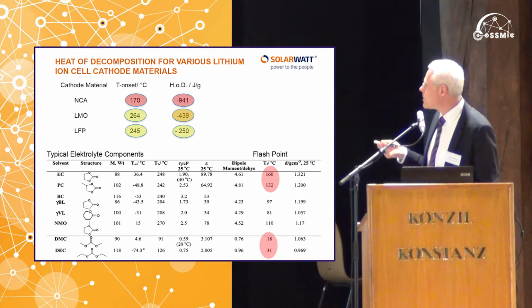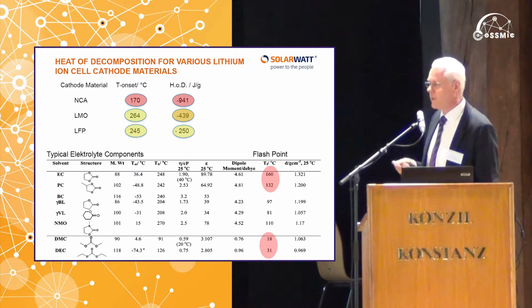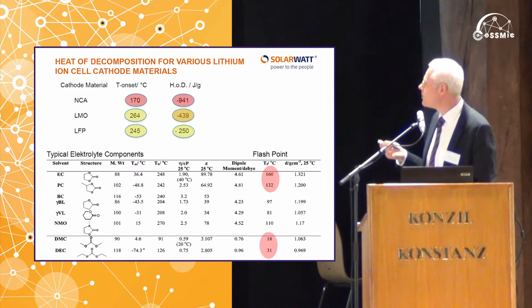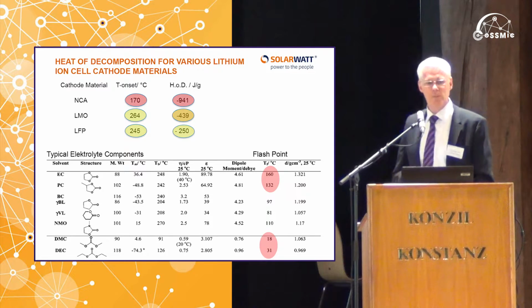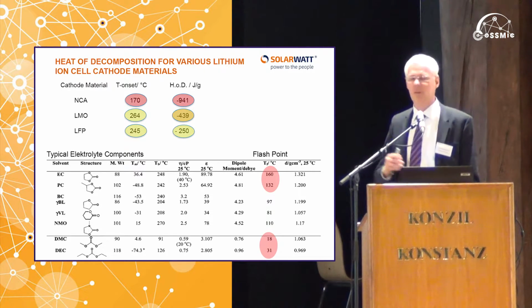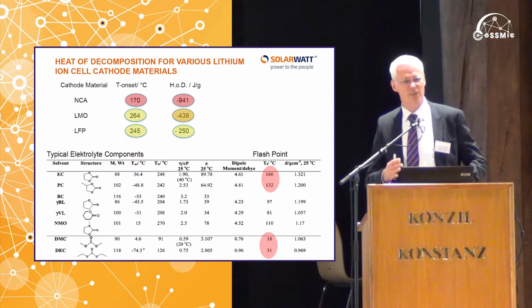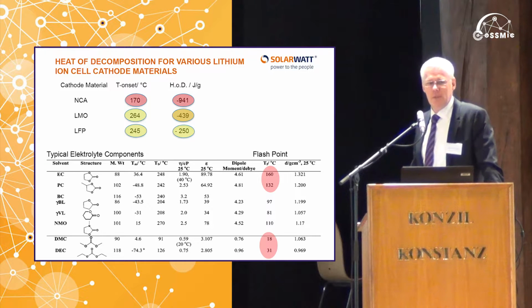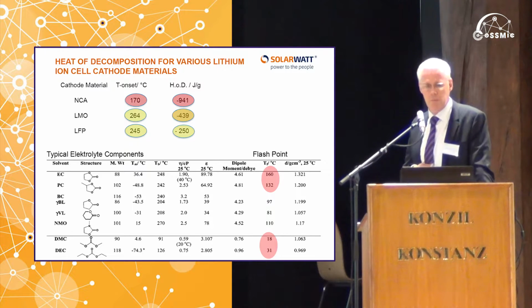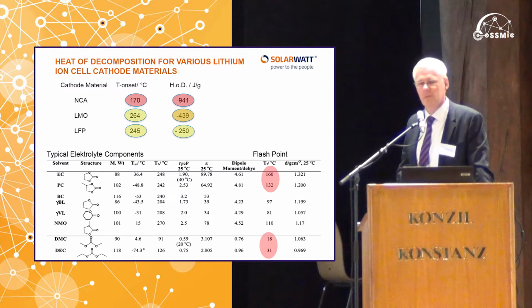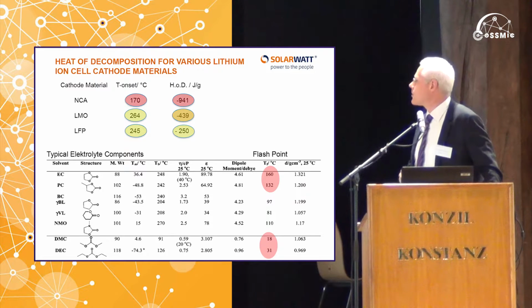On the other hand, the onset temperature at which this process starts is still higher in another material, lithium manganese oxide. So from a safety point of view, you could also argue that lithium manganese oxide is the better material because the thermal runaway starts at higher temperature compared to lithium iron phosphate. So looking into the details, it's not that easy. One can certainly say that nickel cobalt aluminium from a safety point of view is not the best material that you can have. This is the material which is being used in the batteries of the Tesla cars, and which is being used because of its extraordinarily good energy density and specific energy. And there are good reasons to put such batteries in mobile devices, of course.